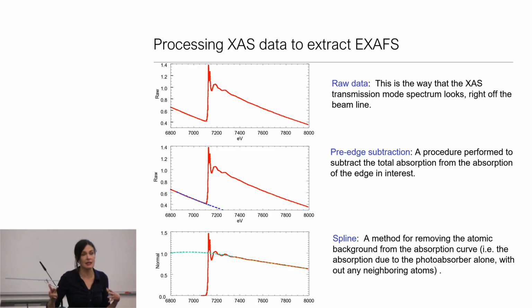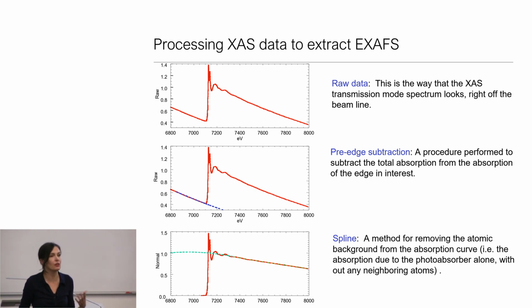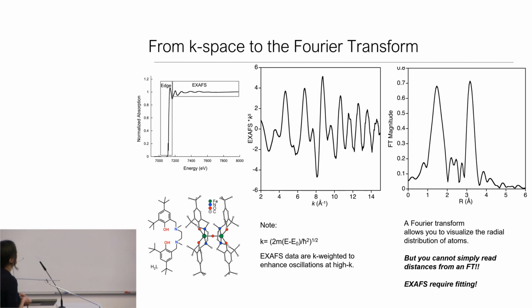So in physics, there's a separate field of people doing atomic EXAFS in the gas phase. But when you're trying to get coordination chemistry information, that's a nuisance, and we're just trying to remove it and somehow model it. These days, most programs have algorithms that just minimize the low R component, and you don't have to think about that too much. In any case, though, this still doesn't look like the EXAFS you see. You can see how weak these oscillations are.